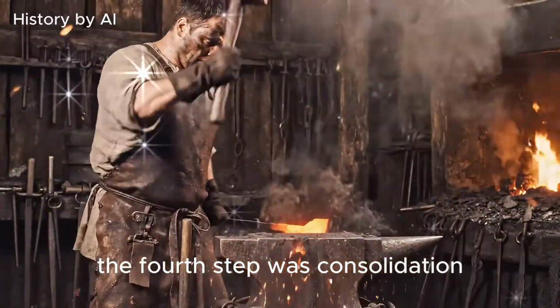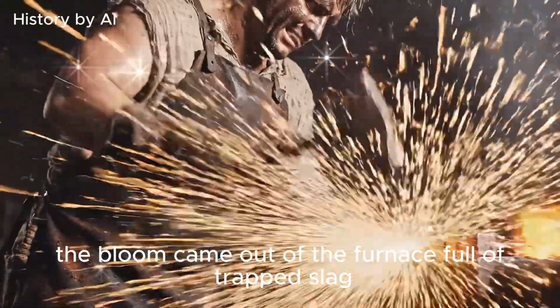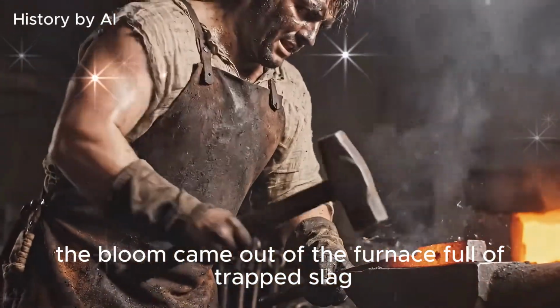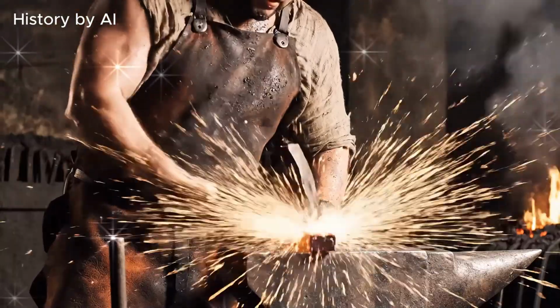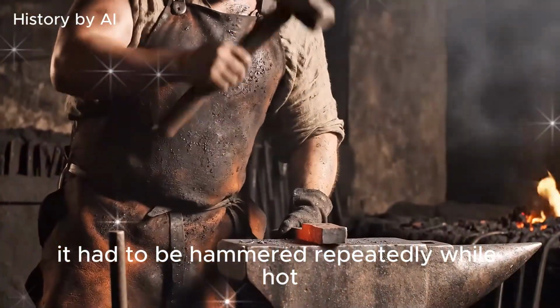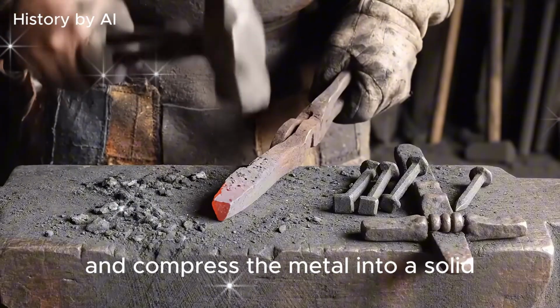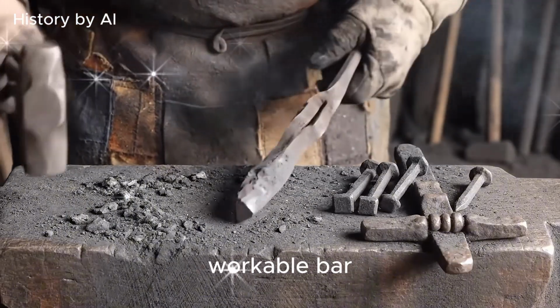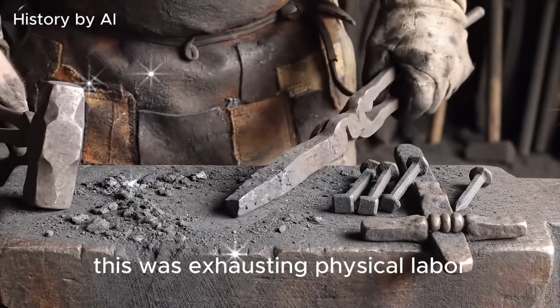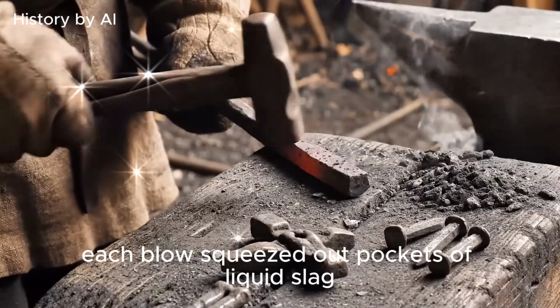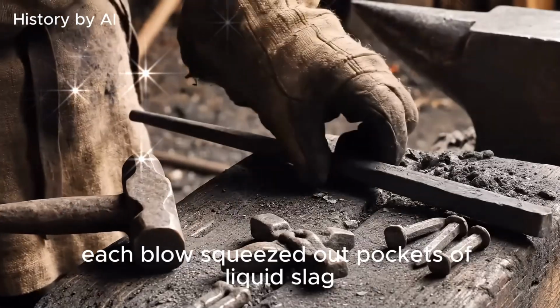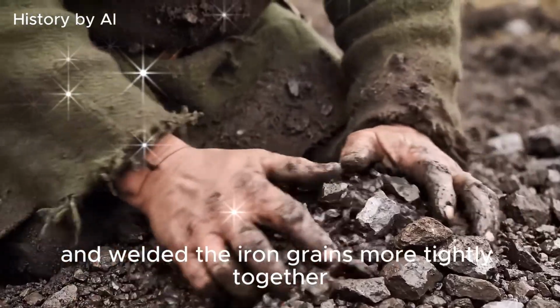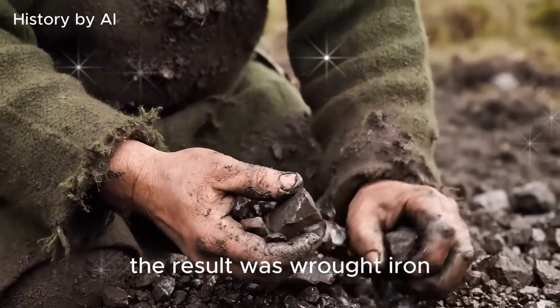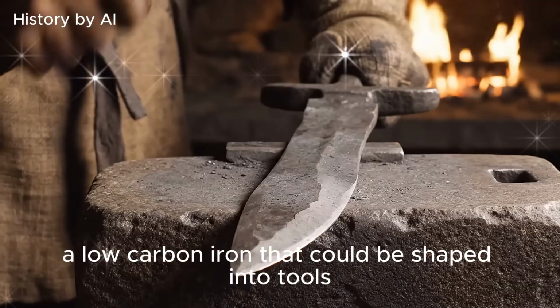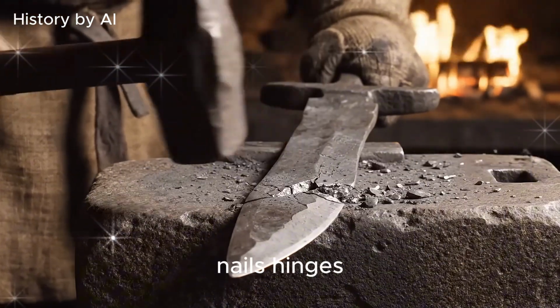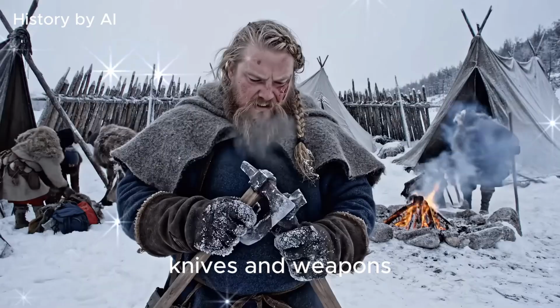The fourth step was consolidation. The bloom came out of the furnace full of trapped slag, charcoal fragments, and voids. It had to be hammered repeatedly while hot in order to drive out impurities and compress the metal into a solid, workable bar. This was exhausting physical labor. Each blow squeezed out pockets of liquid slag and welded the iron grains more tightly together. The result was wrought iron, a low-carbon iron that could be shaped into tools, nails, hinges, knives, and weapons.